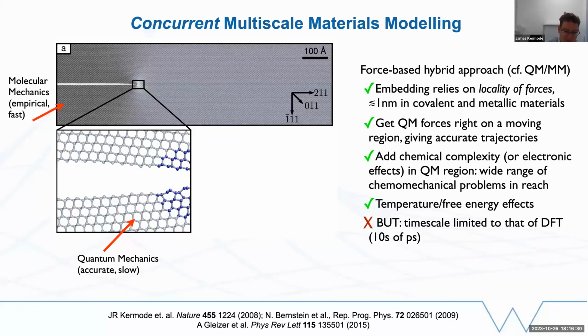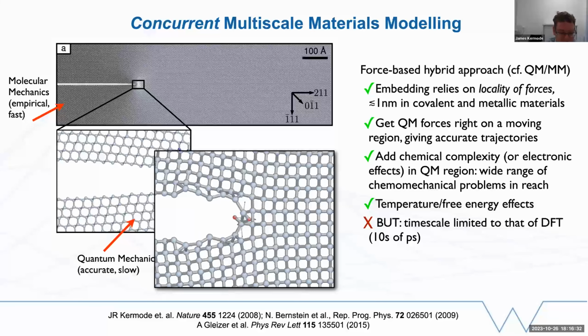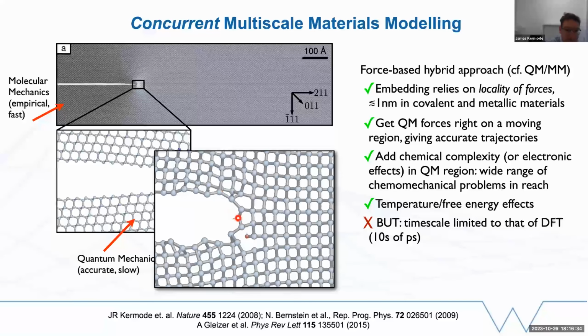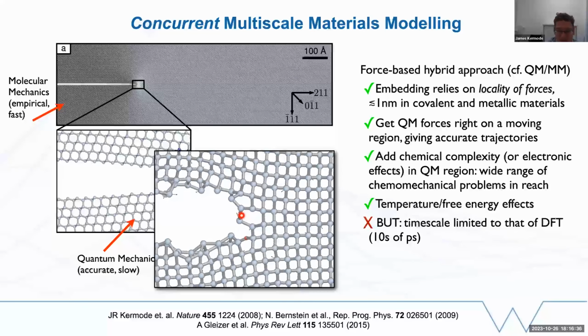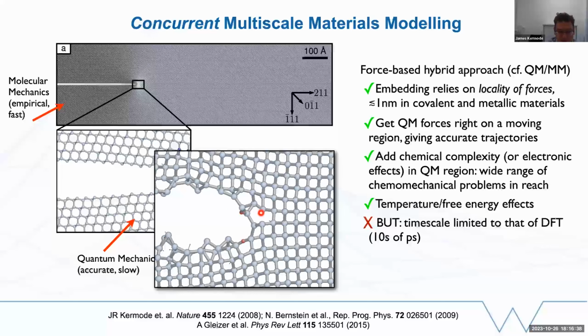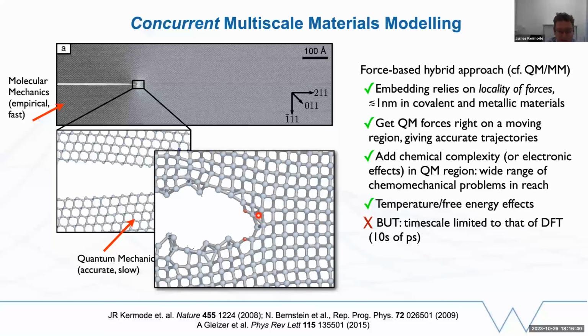We can, for example, look at processes like stress corrosion. So this is where we have molecules from the environment, oxygen, water, etc., that causes cracks to grow at stresses which are insufficient for it to be energetically favorable on its own. We have to keep feeding with chemically aggressive agents in order to promote crack growth.